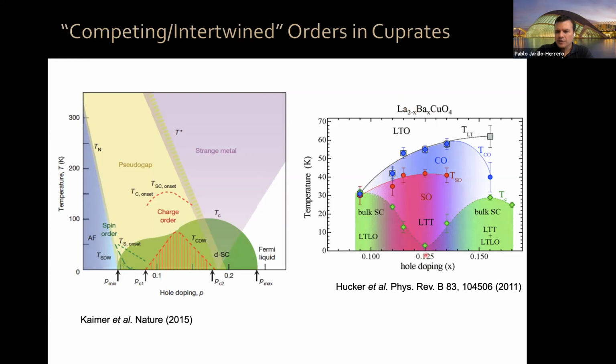And this depletion of Tc is associated with a competition with a competing phase to superconductivity. In this case, it has to do with stripe order, which happens at the so-called 1/8. This is the 1/8 doping anomaly.